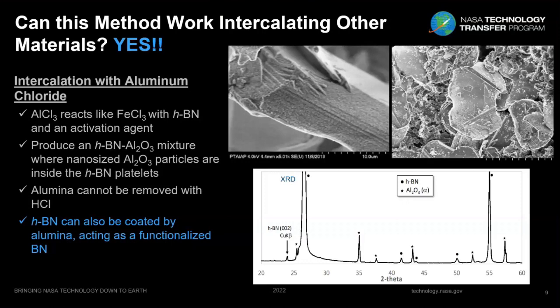One other procedure that we developed was the coating of the hexagonal boron nitride with alumina. That is, you can intercalate and coat or just coat the boron nitride. And here I'm showing some pictures of the presence of alumina. We were doing some coatings and some intercalations with alumina in the hexagonal boron nitride, and the XRD shows the conversion to aluminum oxide, the one that we were expecting.